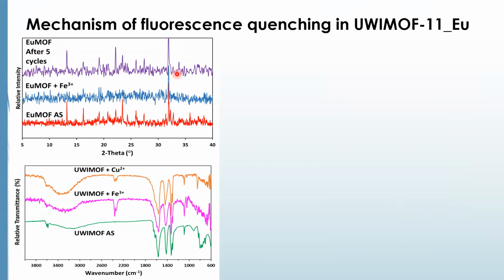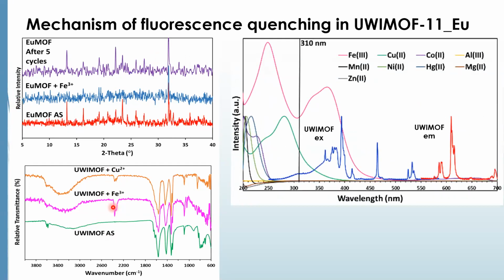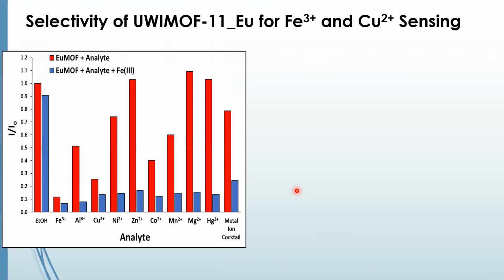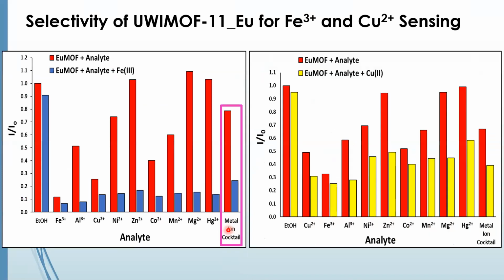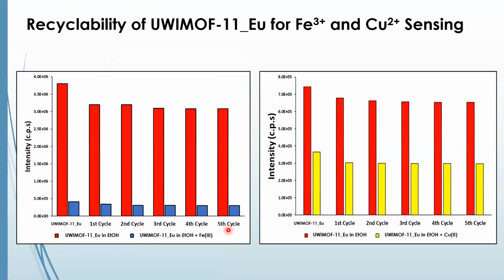So here we're showing the PXRD patterns: as synthesized, this is the PXRD pattern. And with iron, after 5 cycles, you can see the PXRD pattern looking pretty much the same. And in fact, the infrared also looks pretty much the same, showing that there isn't much structural change. And we looked more into the mechanism and noted an inner filter effect of these analytes on the framework. The sensing studies also showed that there was some amount of selectivity: even in the presence of a cocktail of metal ions, there was selectivity for iron and copper. That's what we are showing on these slides.